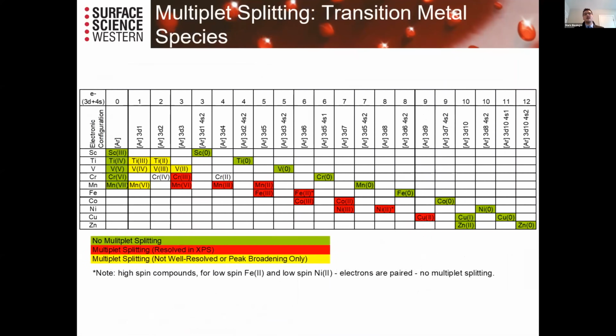The species in red here are those that will show multiplet splitting in their peak shape structure. The ones in green have no unpaired electrons, so they don't show any multiplet splitting. And the ones in yellow have multiplet splitting, but it's either not well resolved or it shows up as peak broadening only.